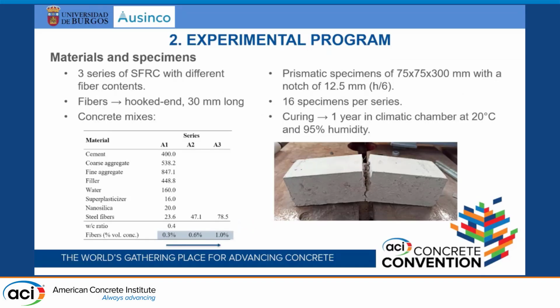So we have manufactured 3 series of FRC, all with the same dosage except for the amount of fibers. This is the same dosage for all the series, A1, A2, and A3. The only component that changes is the amount of fibers, from 0.3% in volume to 1%. And we have cast prismatic specimens of 75 by 75 by 300 millimeters with a notch of 1/6 of the depth, and we have cured them during 1 year in a climatic chamber. Here you have one specimen already broken. Sorry for that.